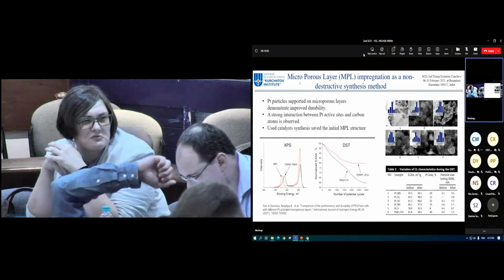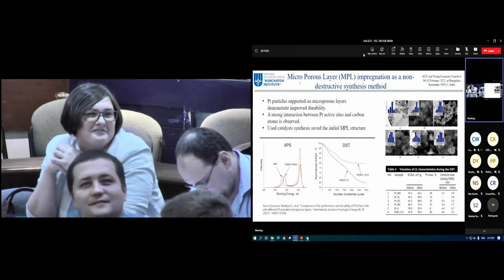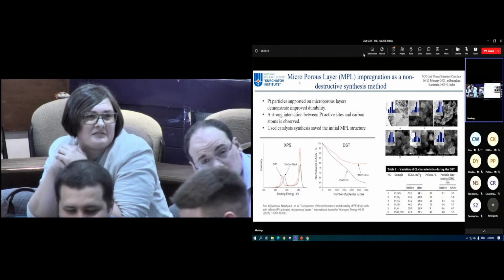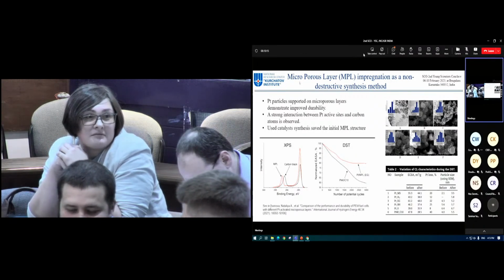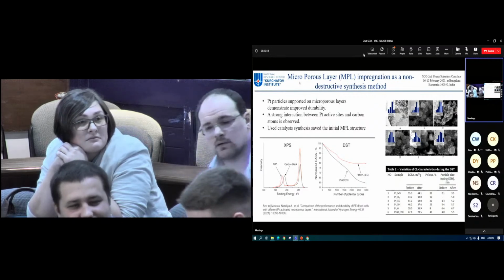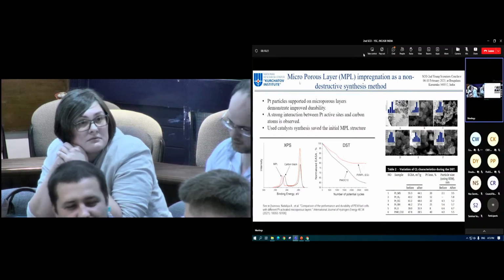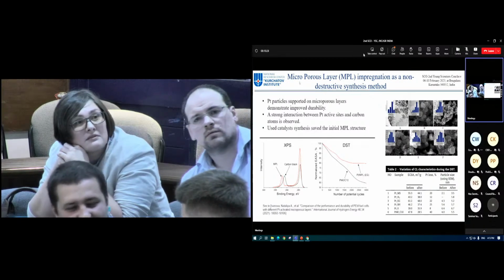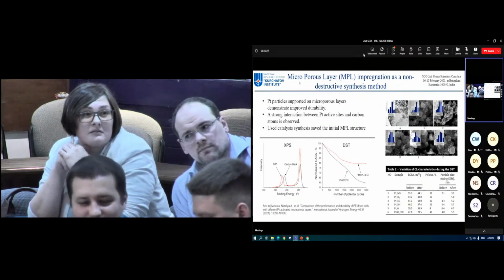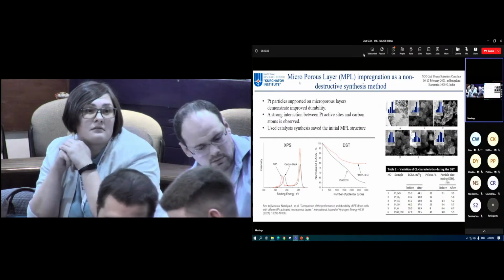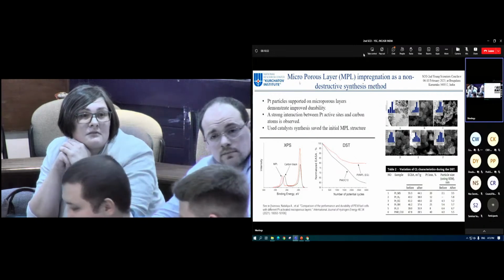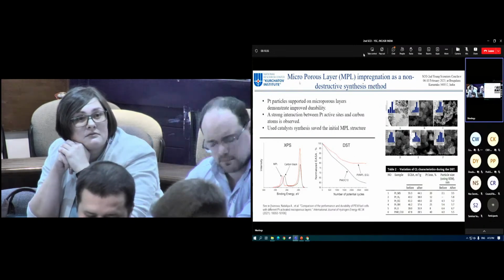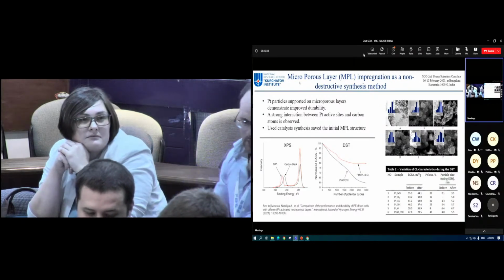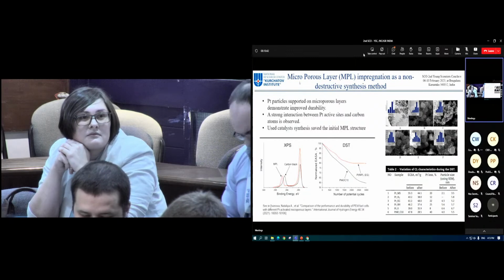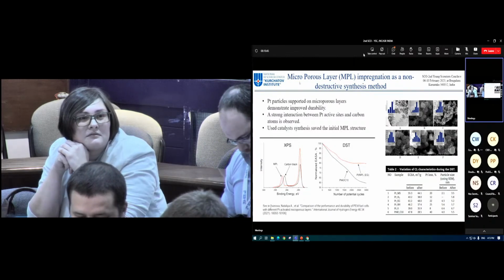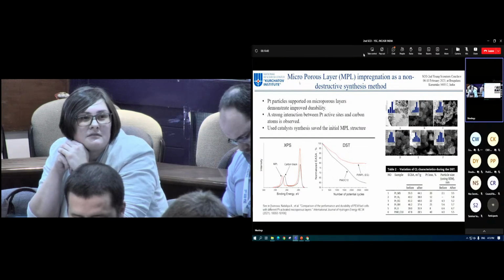And this slide presents the investigation of electrode preparation using impregnation and reducing methods. The durability of these electrodes is approximately 2 times higher than the durability of the reference electrode. A possible explanation for such a result is provided by XPS data. The improvement may be caused by the incorporation of heteroatoms, mainly carbon, in the crystal lattice of platinum particles, leading to stronger mechanical and electronic interaction between platinum particles and surface carbon atoms of the microporous layer.